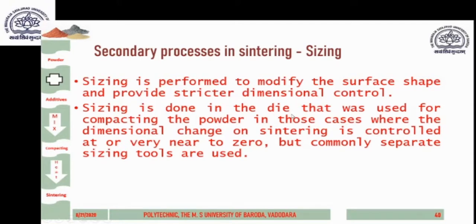Sizing is done in the die that was used for compacting the powder, in those cases where the dimensional change on sintering is controlled at or very near to zero, but commonly separate sizing tools are used. Okay, so there are 2 points in this statement: sizing may be done in the die which was used for making the green compact, or they may have special dies which are built just to conform and to make the required shape and size of the product after sintering.